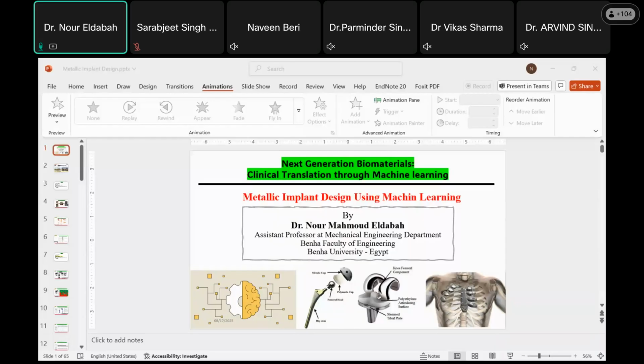And you should bear in mind that some biomedical alloys like titanium 6-4, cobalt chrome molybdenum, or 316 stainless steel all contain some elements that are not accepted for implantation. That's why we need research and development in the field of biomedical alloys to replace the toxic elements inside the base and to invent new alloys.